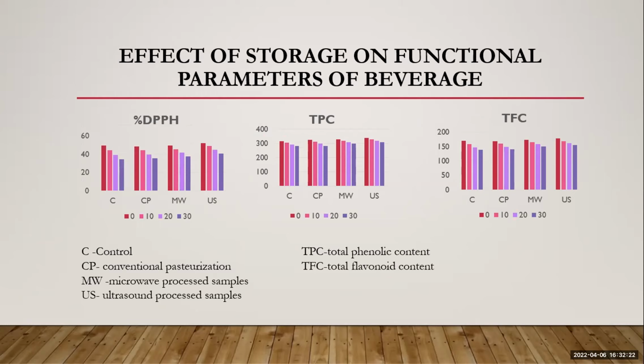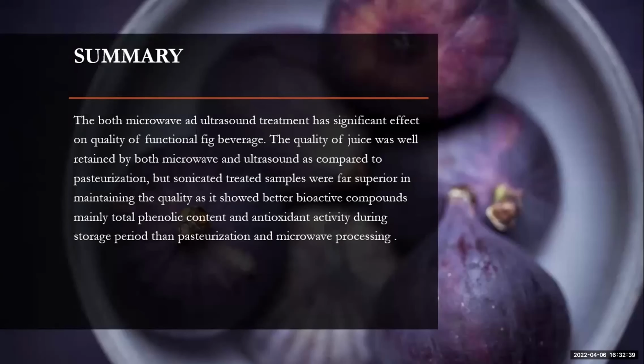The DPPH, total phenol content, and total flavonoid content gradually decrease over the period of 0 to 30 days. In microwave and ultrasound samples, the decrease is much less compared to the other samples. Both microwave and ultrasound treated samples have a significant effect on the quality of the functional fig beverage. The quality of the juice is better retained by both microwave and ultrasound as compared to pasteurization.